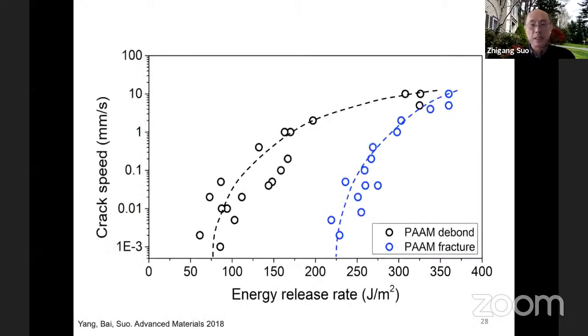By doing peeling tests, we apply energy, apply load. Load divided by width is this energy released, joule per meter squared, and we measure crack velocity. You can see we compare two cases. The blue dots are just one piece of polyacrylamide—you don't have chitosan. Then you really need to apply a high force to break this. But if you use chitosan to bond this polyacrylamide, the force becomes lower.